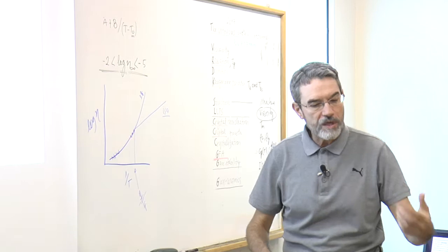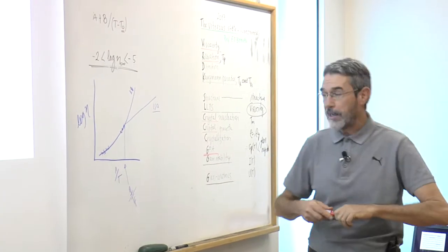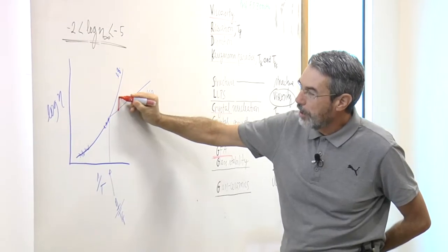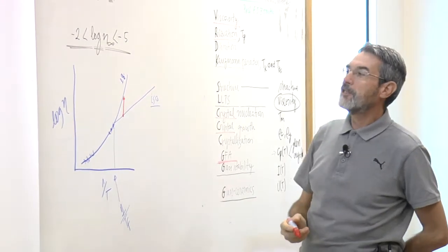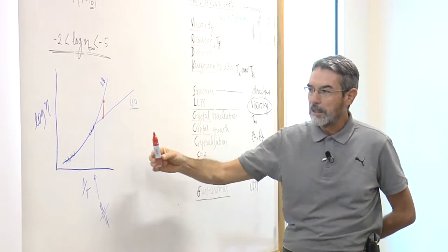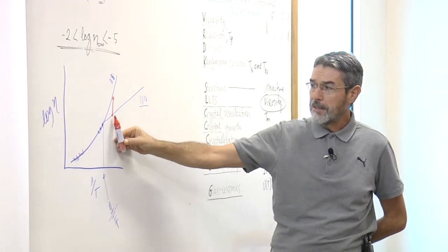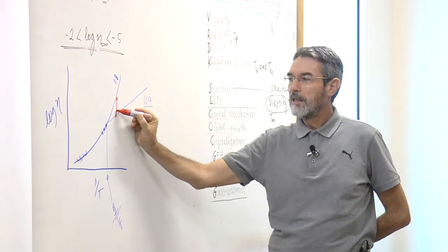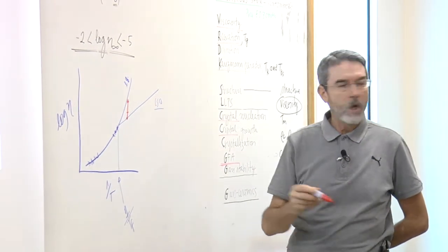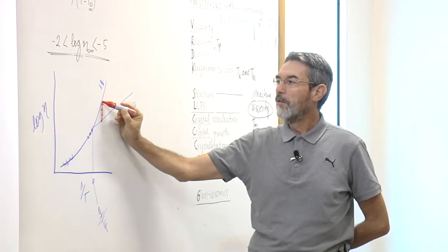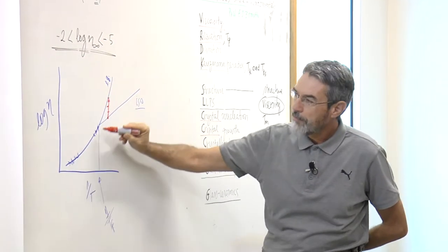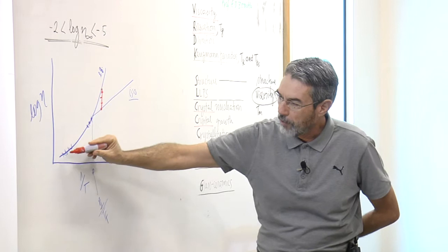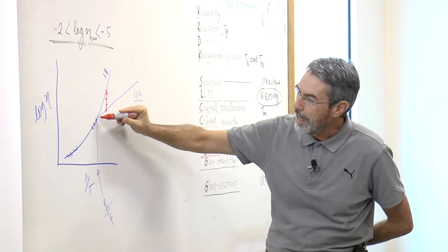The relaxation process we are going to talk about next week refers to relaxation from here to here. This is the relaxation process that takes place below Tf or Tg. The glass starts with isostructural viscosity. If you wait some time, the viscosity will move here. If you wait longer, it will move here. Wait longer, it will move until it reaches the equilibrium viscosity curve, which is extrapolated from the equilibrium viscosity data points that we measure.